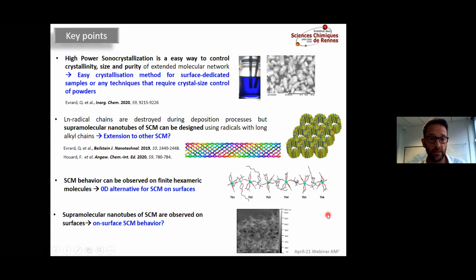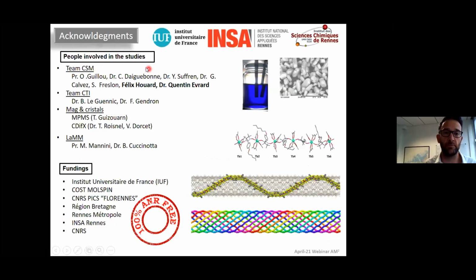We have also shown that we can have an alternative to the single chain by having these long linear molecules that behave as single chain but are finite molecules. And we are looking for time and beam time at a synchrotron to be able to observe an on-surface single chain magnet behavior. So these are the people involved in the study, people from the lab, people from the theoretician side that help in magnetism in crystals, and our inter-influence for the AFM measurements, and the fundings.